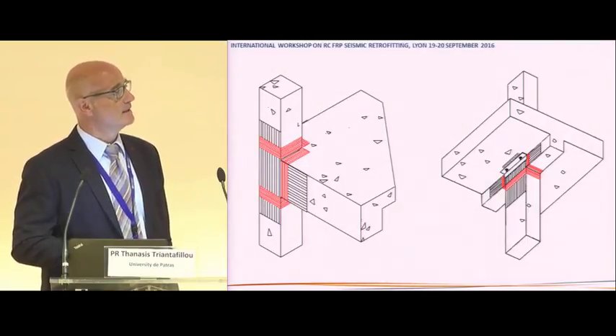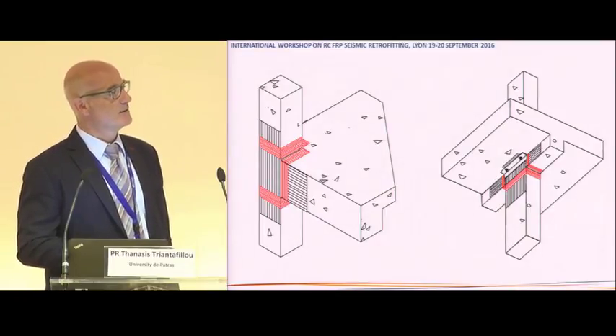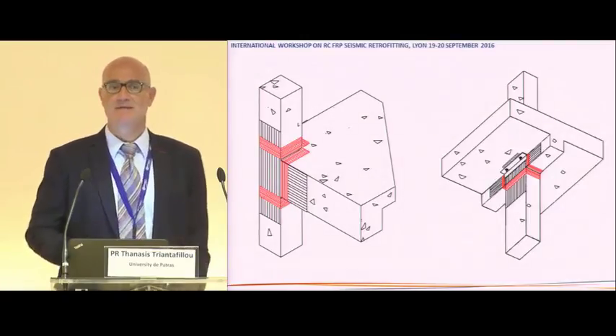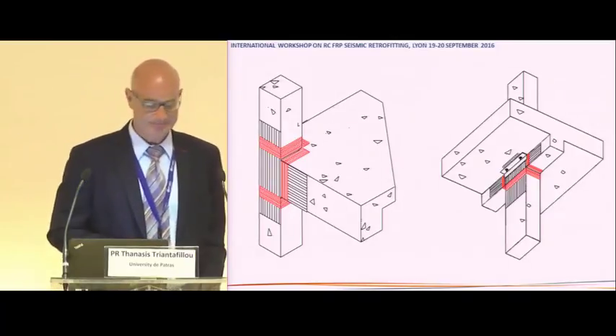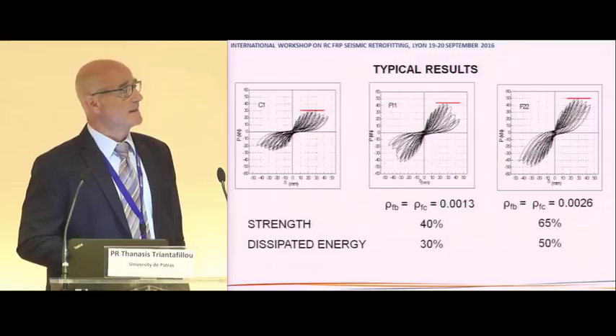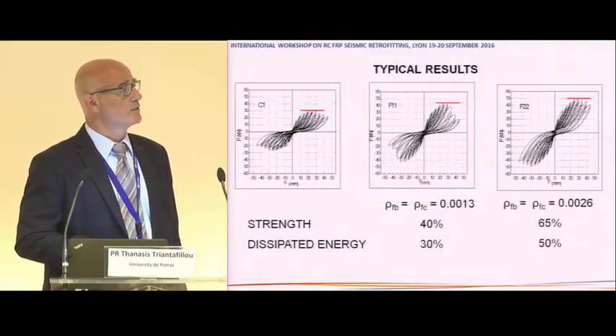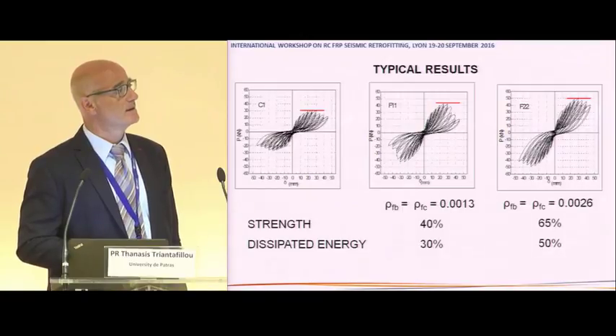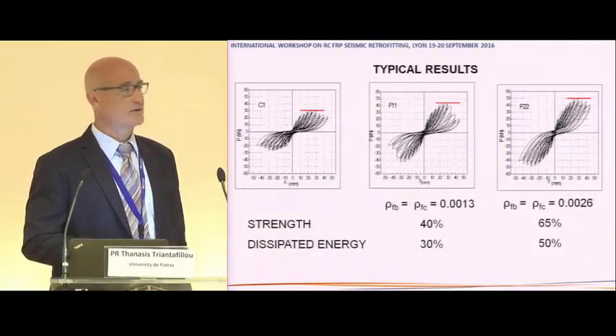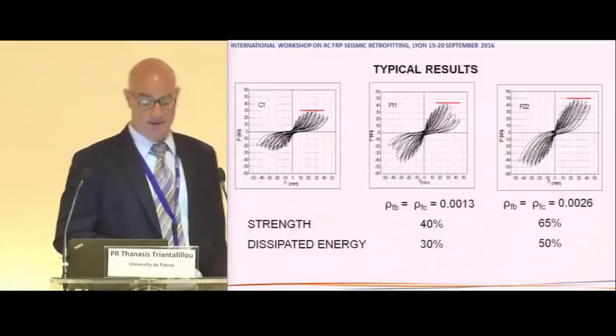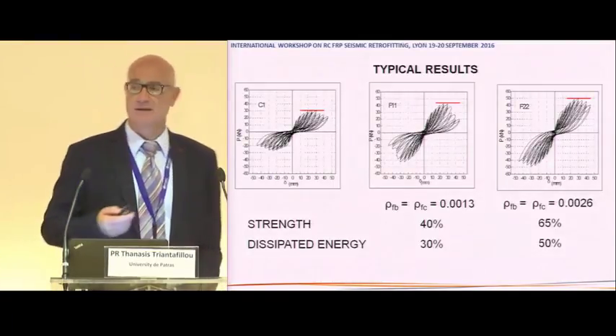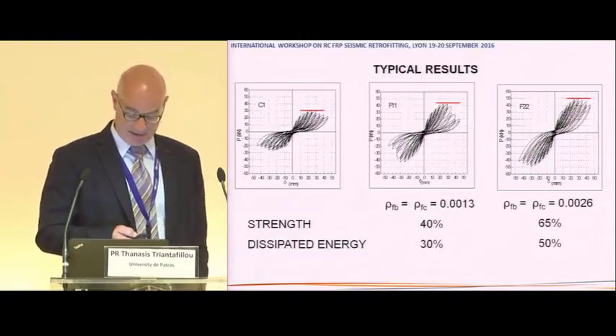And it's really important to emphasize here that simply placing fibers in the joint panel is not enough. We really have to extend the fibers outside the joint to properly anchor those fabrics so that the fibers in the joint region will be activated before debonding takes place. That's a typical response of a joint without any retrofitting, and you see how the shear capacity of the joint may increase with one or with two layers of a low-cost, low-thickness CFRP fabric. We get increases in strength in the order of 40 to 60, 70% easily with a couple of layers.